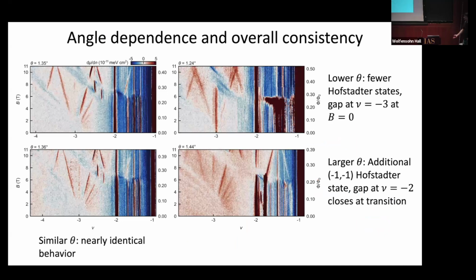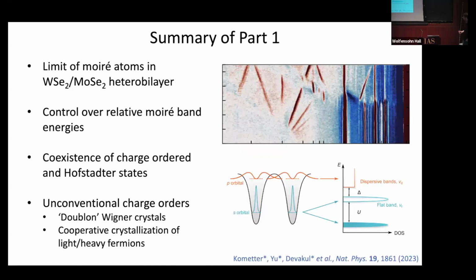So all of this is very robust. We can look in different parts of the sample in areas that have similar twist angles. We see almost identical phase diagrams. Actually, if we decrease the twist angle, that tends to flatten the bands, and this Hofstadter state disappears. There's an extra incompressible state that we see at nu equals negative 3. As we increase the twist angle, you get an extra Hofstadter state here, so basically, this is all consistent with our picture that when you have flatter bands, you tend to favor charge-ordered states, and when you have more dispersive bands, then you form this electron liquid and see Hofstadter physics emerging.